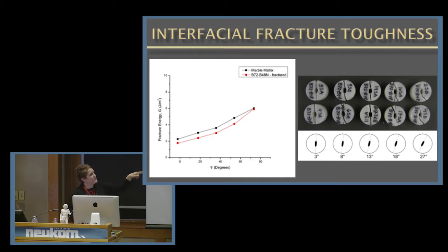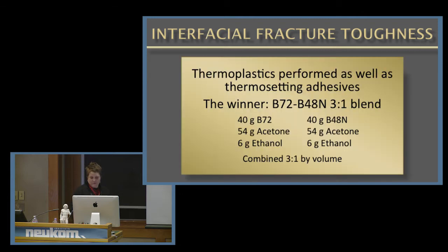The one that matched the stone energy plot closest was a blend of B72 and B48N. And these are two acrylic adhesives that we are quite familiar with in conservation. And they also had the thinnest join. So we had a combination of a reversible, familiar adhesive that had the thinnest glue join. So we had a winner for our adhesive. This is after a year of study. So here's our winner. It's a blend of these two acrylic adhesives.